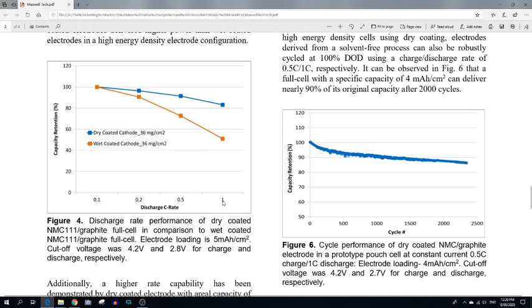You can see that if you charge or discharge within an hour, the dry-coated cathode retains much more of its capacity. Basically, the wet cell, as you start draining or charging it, heats up. You get a lot more internal resistance, and the capacity at that point is reduced considerably. And it looks like, by about 50 versus 90, it's about a 40% difference, or 30% at least. So I imagine that continues to get even steeper as you move towards something like a half-hour charging time.